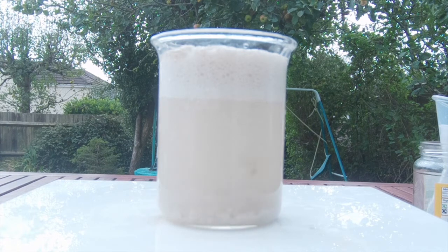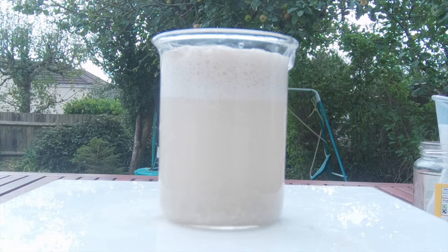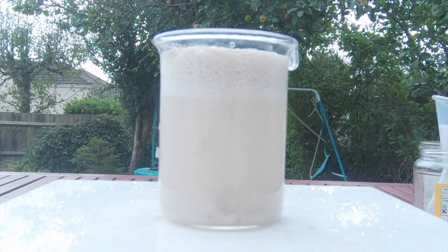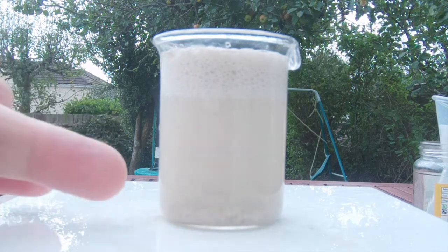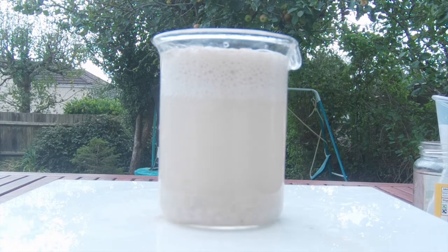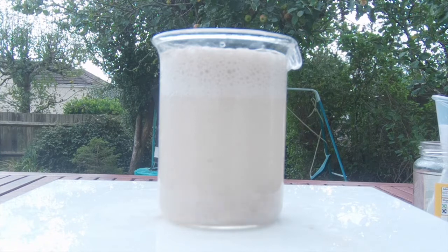But I've used mineral water here, so it has bubbles inside. Where there is a bubble, there is no water. So these micas will have a tendency to attach themselves to these tiny bubbles in the sparkling mineral water, and the bubbles will carry the micas to the surface. The quartz and feldspar, if this works, will all stay within the water or settle at the bottom. I'm going to leave it to stir for a bit so all the micas have a chance to attach to the bubbles and be pulled up to the surface.